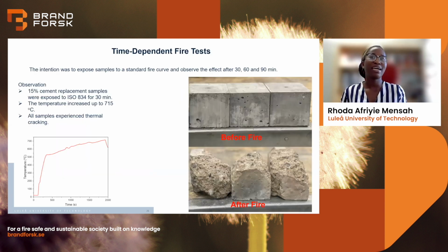We also did a time-dependent fire test. With this test, we had the intention of exposing the samples to the standard fire curve, that is the ISO 834 curve. And then we wanted to observe the changes in the concrete after 30 minutes, 60, and 90 minutes. For this test, we used the 15% cement replacement samples because the difference in the strength and modulus were similar to that of the 0 and 10%.